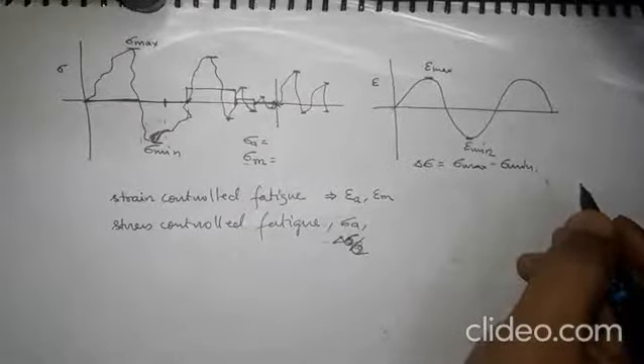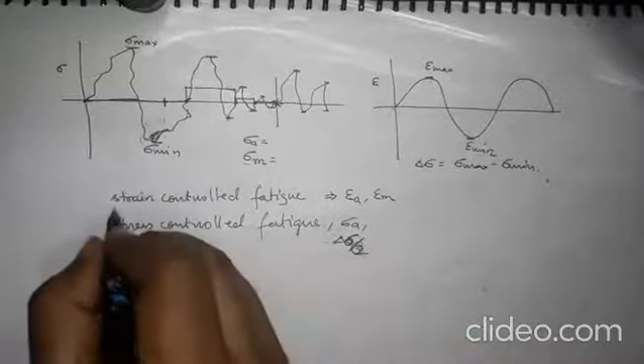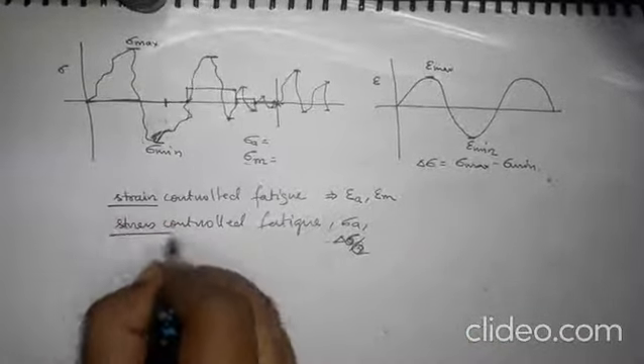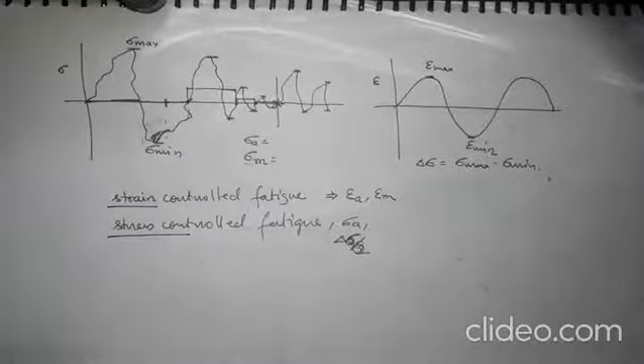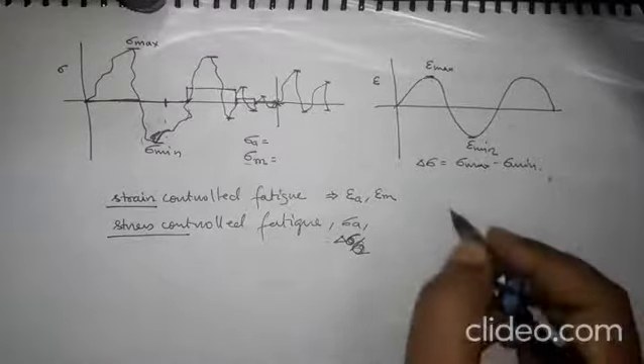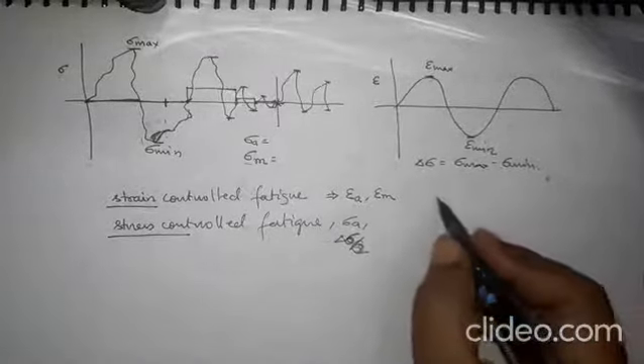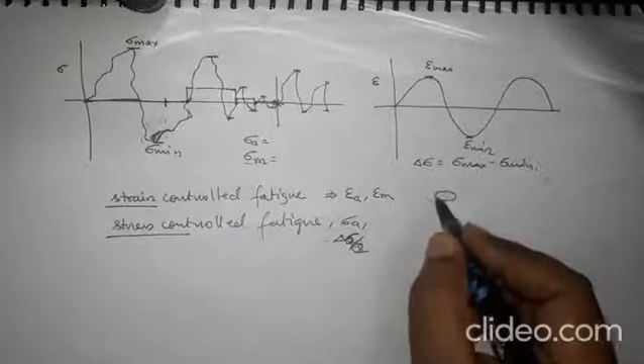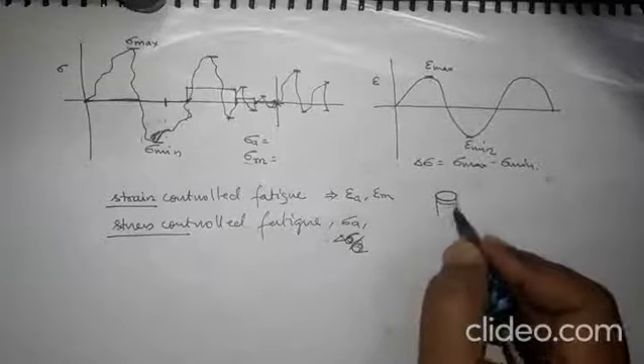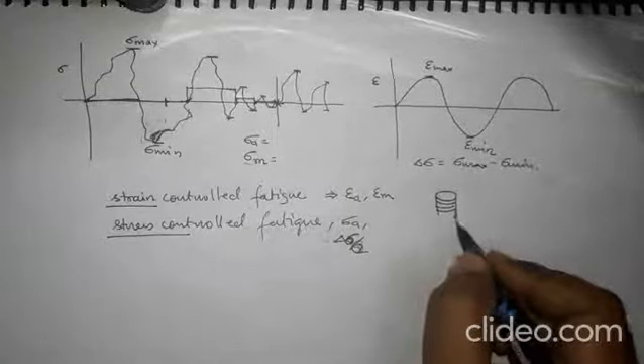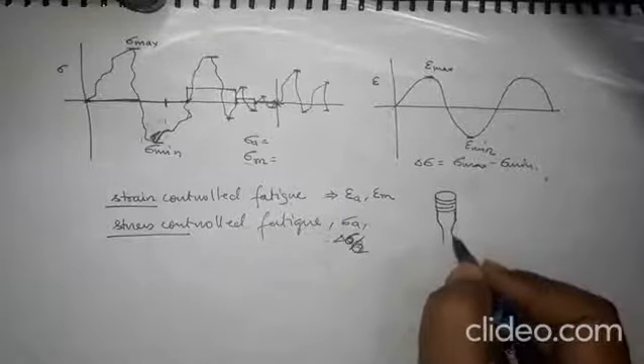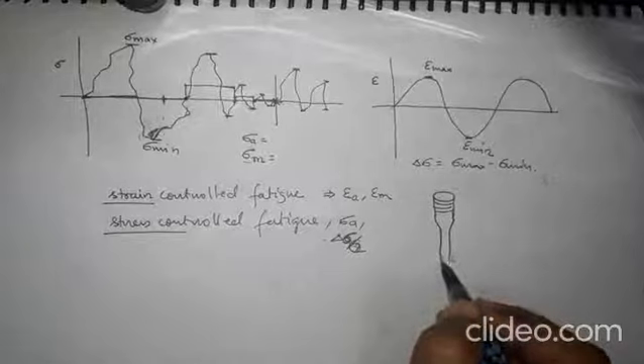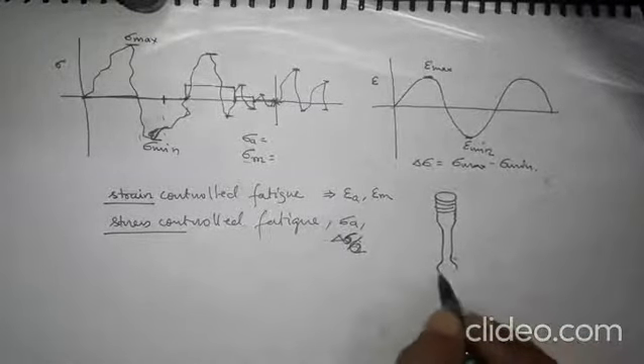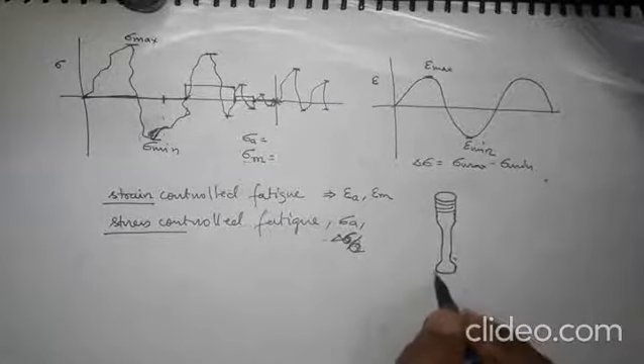Okay, so the testing is usually performed by defining the strain, or you can do it by defining the stress. So you can have a cycle of stress or you can have a cycle of strain. It is possible both ways. So the testing of fatigue is performed similar to the tension test. The specimen usually looks the same. You have threads to fix the specimen in the machine, and then you have a dog bone kind of specimen with a parallel gauge length, and then you have the grip section, and then you have threads again.